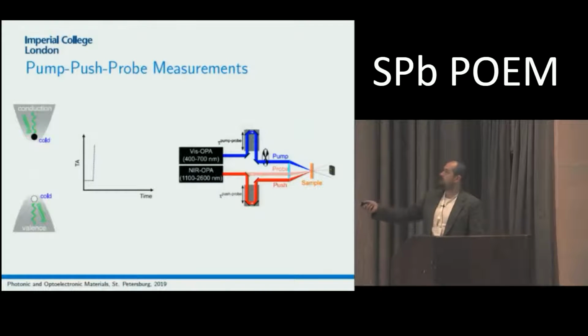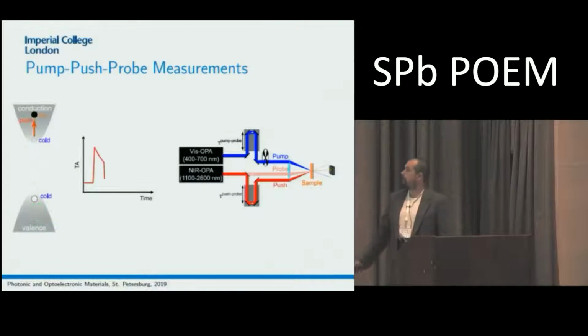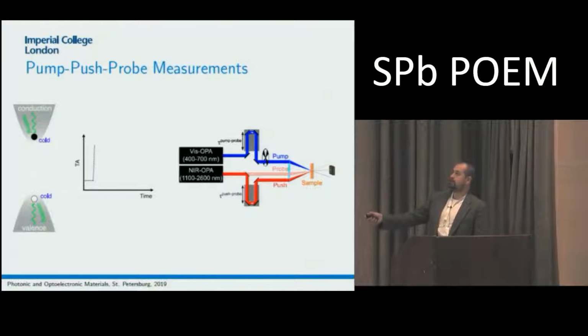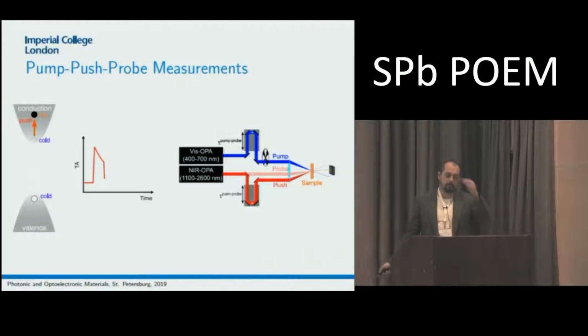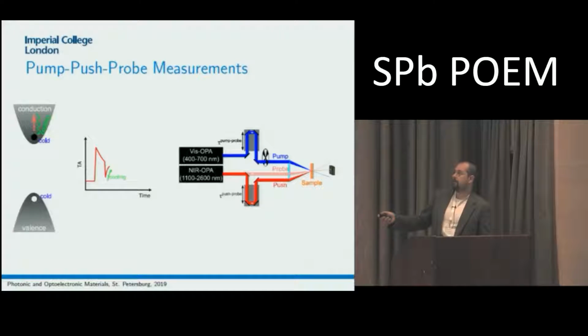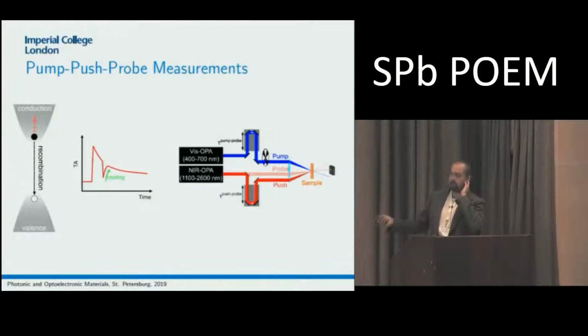So what is happening here is that we have not just two pulses, pump and probe, but we also have another really powerful signal, which we call push. And what processes are happening here? First, again, we pump the sample, and we see the drop of transmission in the probe signal. Then the carriers are cooling to some extent. Then the push pulse arrives. Once the push arrives, we can see the bleach of transmission, and then upon carrier cooling, the transmission just comes back to the normal pump-probe curve, and then follows the normal relaxation process and recombination.